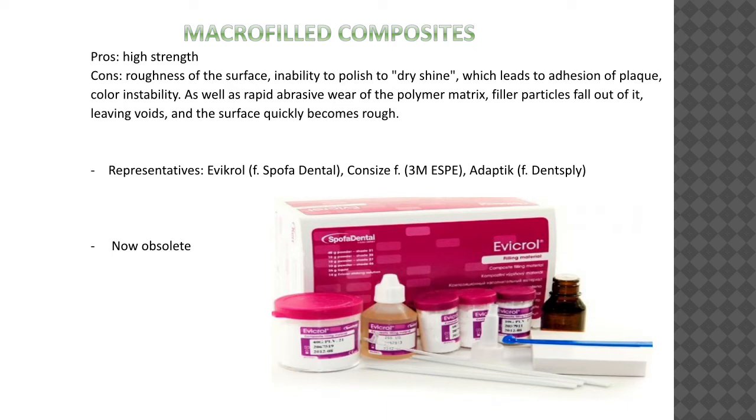Filler particles fall out of it, leaving voids, and the surface quickly becomes rough. The representatives are Evicrol by Spofa, Concise by 3M ESPE, Adaptic by Dentsply. Nowadays, these composites are obsolete and are not used anymore in practice.